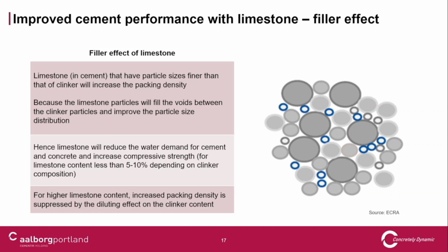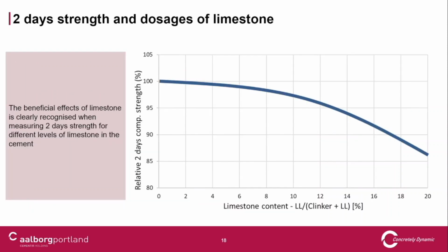If dispersed, not flocculated, this filler effect will densify our cement paste and help increase strength further. We can see these three effects combined quite clearly when we look at the 2-day strength of a limestone-filled cement. This graph shows from 0 to 20% limestone, and the 2-day strength relatively, with 100% being the strength at 0% limestone.